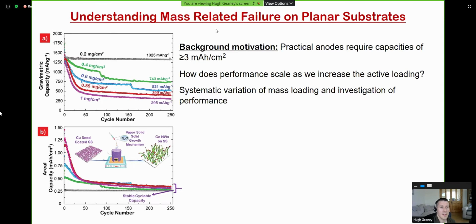Some of the motivation here was that for a practical anode, we're going to need a capacity of over 3 milliamp hours per centimeter squared. So the question at the start was, how does this performance scale as we increase the active loading? So I wanted to systematically vary the mass loading and investigate the performance. You can see the loading of the different anodes as we continue along here, up to 1 milligram per centimeter squared. It's quite obvious that as we increased the loading on these anodes, the gravimetric capacity started to decrease.